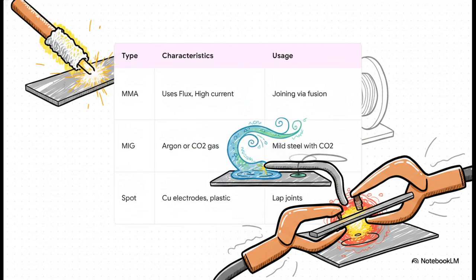Then we look at autogenous resistance spot welding. This is an entirely different beast. It uses copper electrodes to physically pinch 2 sheets of 0.6 millimeter mild steel together, passes a massive current through them until they hit their plastic point, which is just below melting, turning red hot, and fuses them together without any filler metal or flux whatsoever.